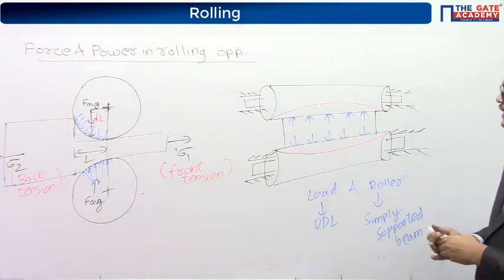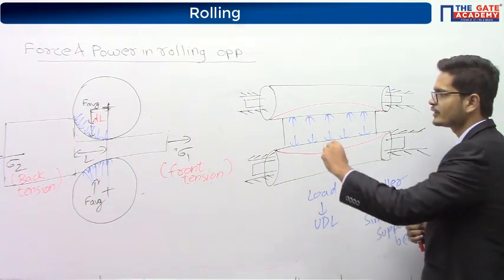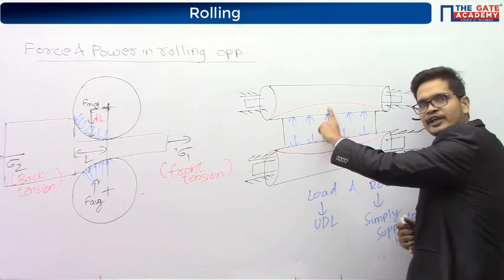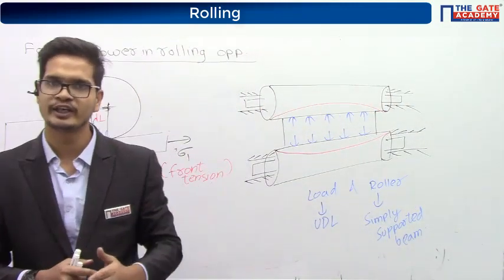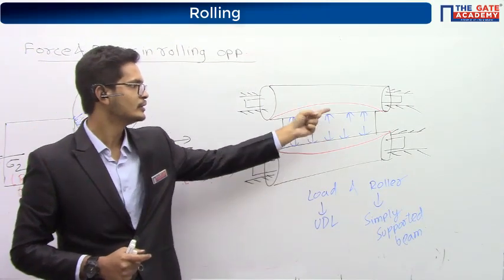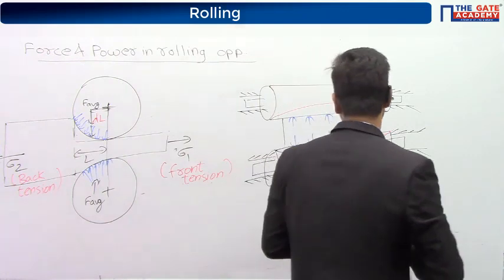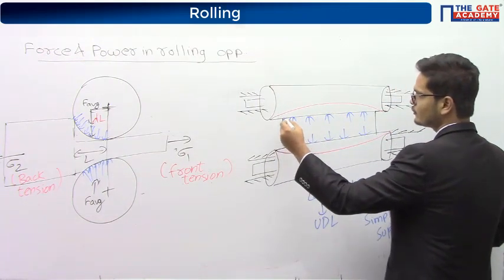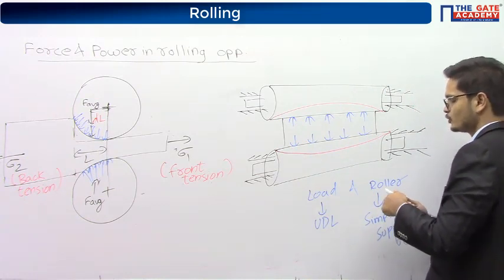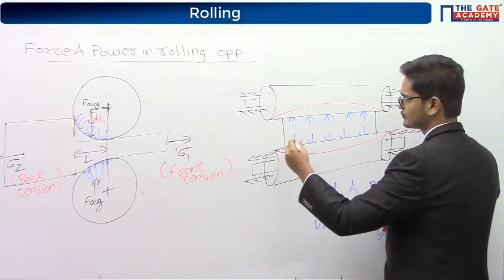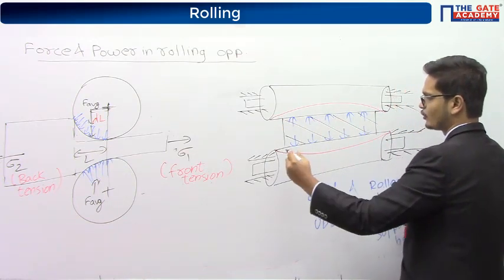So what is happening here is, the rollers are bending, right? So in between some gap will be created, and this gap will get filled by the material. Because of that, the material will become non-uniform in thickness. Let's say this was the material. Now it has become this.